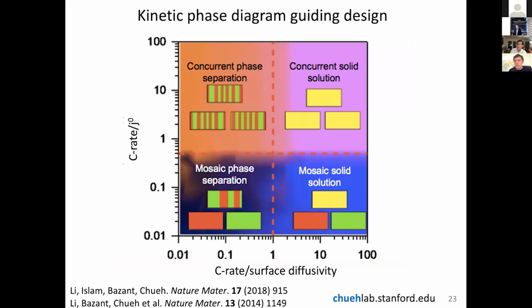So let me take all of these rules and put it into a phase diagram. So for battery engineers, we're constantly thinking about, well, how do I engineer the material to be uniform and homogeneous? After all, this is what can give rise to excellent reversibility and lifetime. It turns out that you actually want a fairly resistive battery, because when you have a resistive battery, you can use that interfacial resistance to suppress phase separation. And it also turns out you need to have a very low surface diffusion coefficient so you don't allow the material to phase separate within the particle.